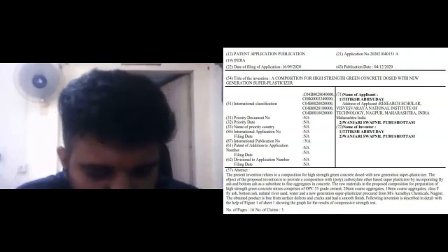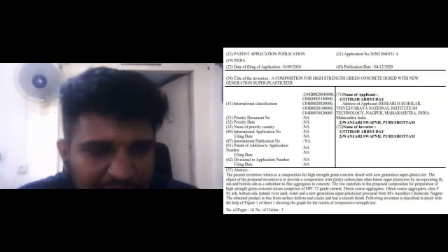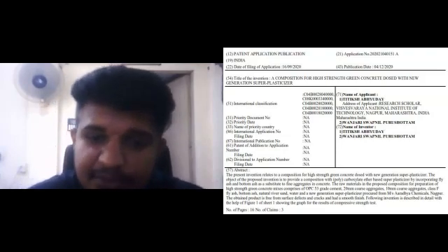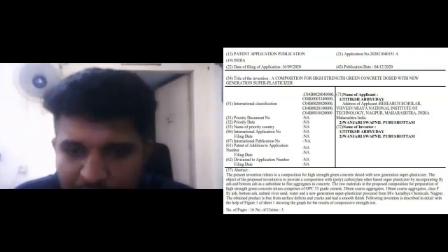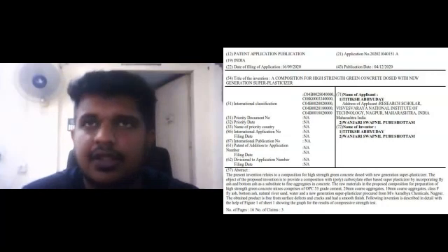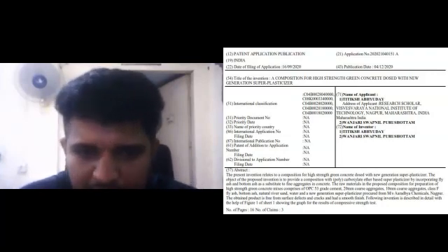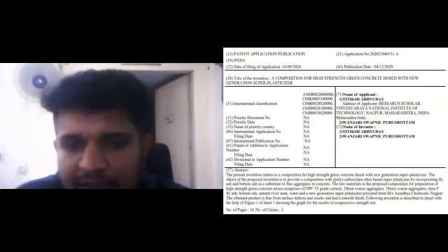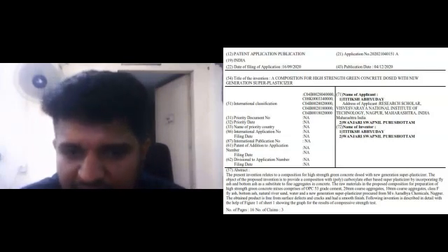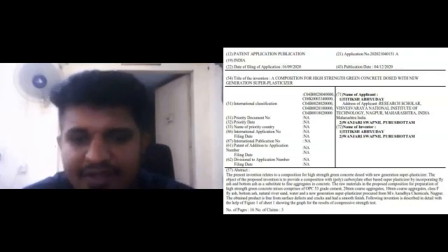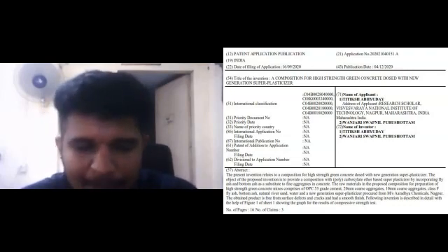See, when I said I am incorporating fly ash and bottom ash in a quantity equivalent to 500 or 600 kg per cubic meter, we had to tweak the concrete mix design a little bit. In a conventional mix design, in any concrete, the aim is to minimize the interparticle space, or as we call it, the void spaces in between the particles. You're using aggregates or stones, and to fill up the gap in between the stones, you use filler materials such as river sand. And the cement in concrete is actually the binder which holds all these sand and aggregate particles together. The complete aggregate and cement matrix as a whole is what we term as concrete.